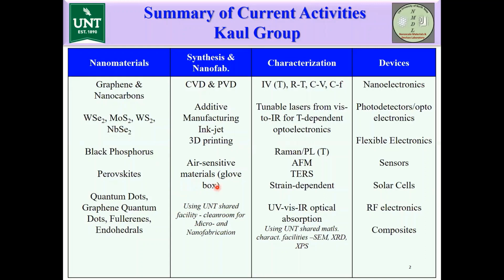For air-sensitive materials processing, we use a glove box, and we also use one of the UNT shared facilities, which includes a clean room. To study the electrical behavior of these materials, we have an IV station from Lake Shore Cryotronics, which has cryogenic capabilities to go down to temperatures as low as 4 Kelvin. We also have different lasers which can go from 300 nanometers to 1100 nanometers. We have an instrument from Horiba which includes temperature-dependent photoluminescence and Raman spectroscopy, atomic force microscopy, and tip-enhanced Raman spectroscopy, and a few of the other characterizations that we use from UNT shared materials research facilities,